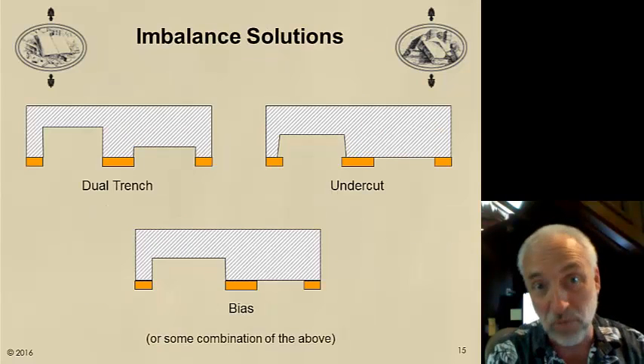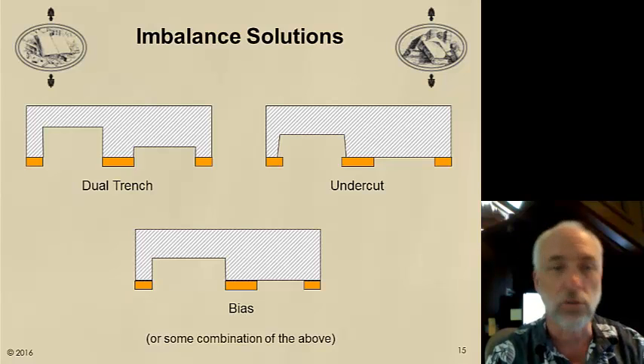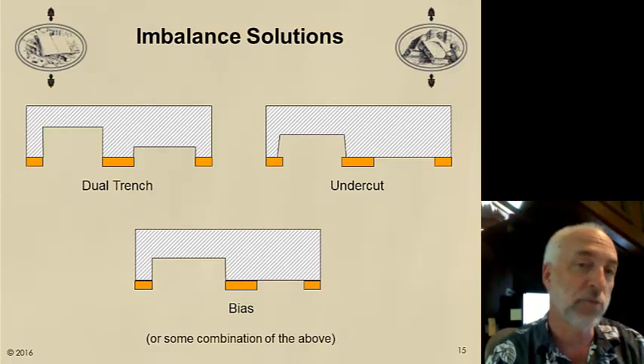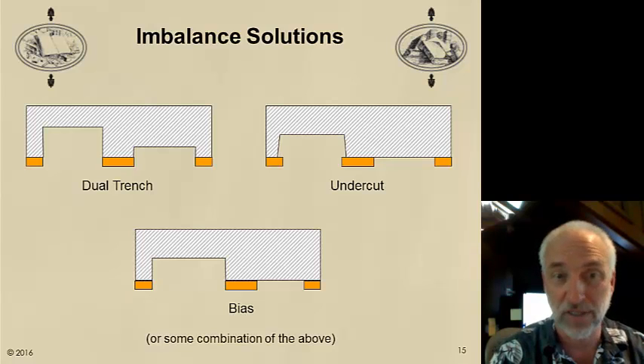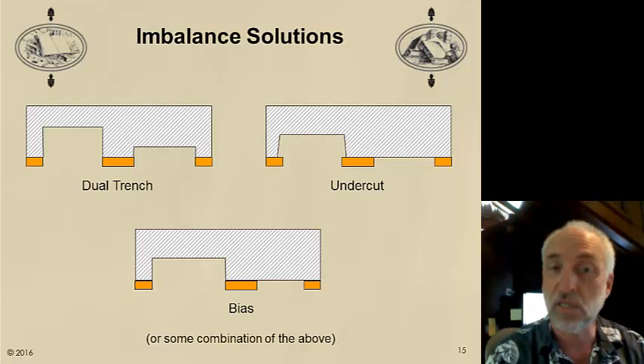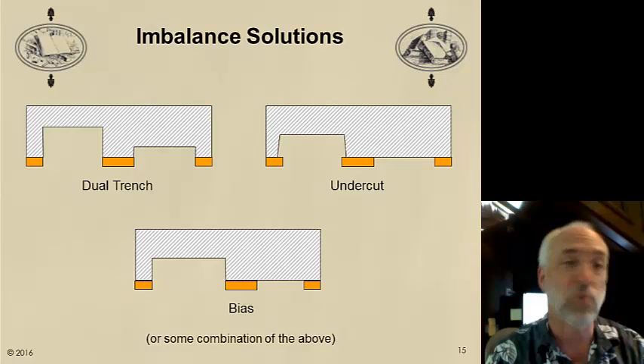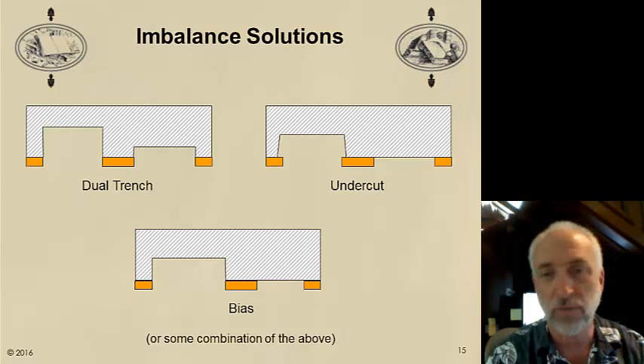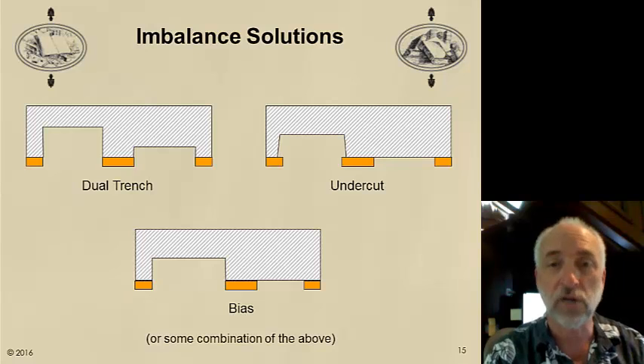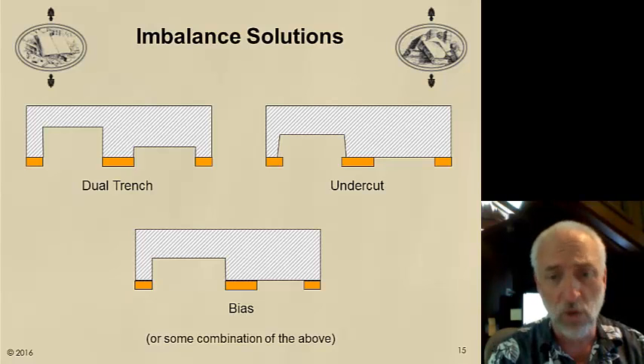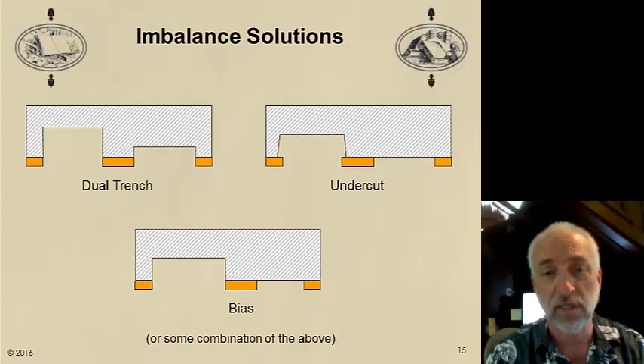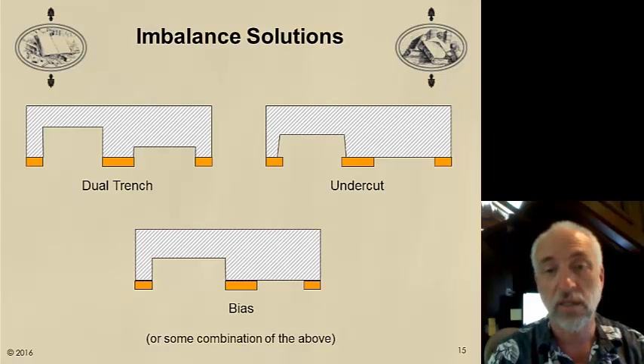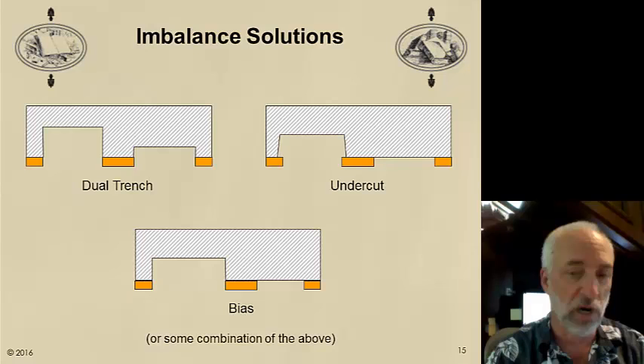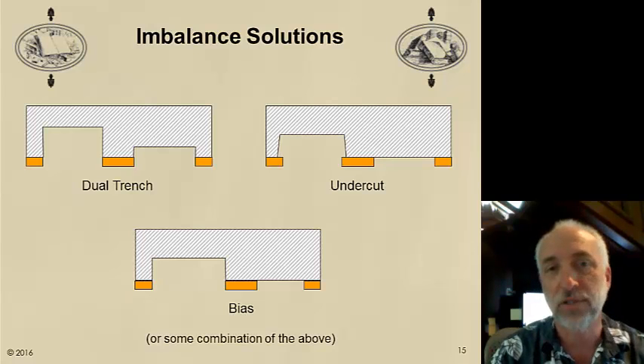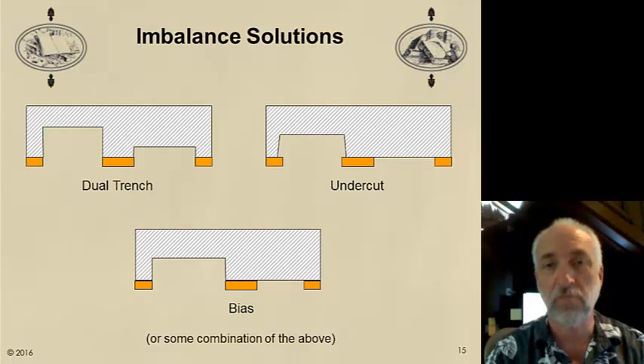We fix it in the mask making process. There's a number of different imbalance solutions that people have tried. A dual trench means we keep the relative difference in the thickness between the shifted and unshifted space the same, but we etch a little bit into both. This helps, doesn't quite solve all the problems. We can do a little undercut on the phase shifted space, the etched space, and that undercut can increase the transmittance a little bit. Or the simplest solution is to bias the phase shifted space a little bit, make it a little bit wider than the other space. Or we'll do some combination of the above. Well, these add extra complications into the mask making process for an alternating phase shifting mask.